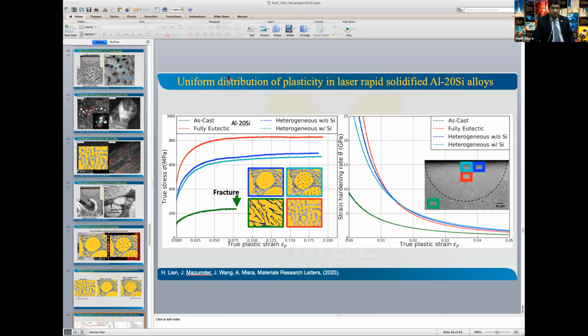Yeah, that's a good question. That's exactly what we are working on now. We are going back and characterizing a lot more of these melt pools under different conditions to understand why you get these different morphologies. We have been able to nail it down that there are 3 distinct morphologies. And it seems the fully eutectic, which is shown in that red box, is in the middle part or lower part of that pool, where the cooling rate might be slightly lower.